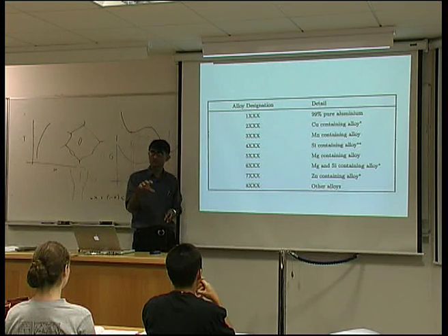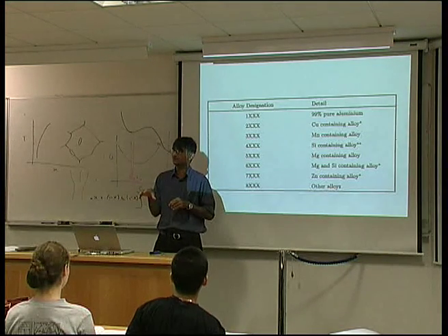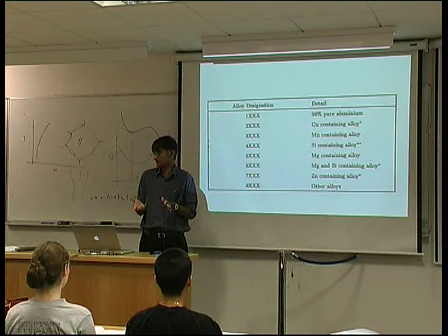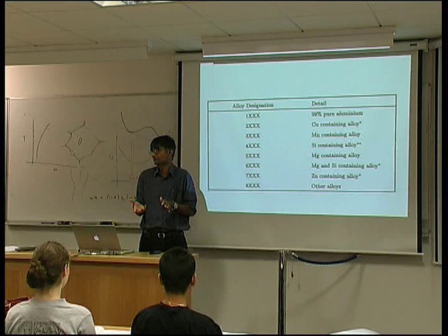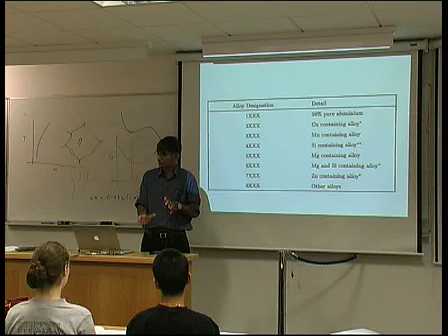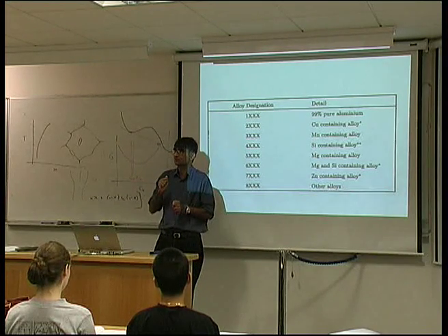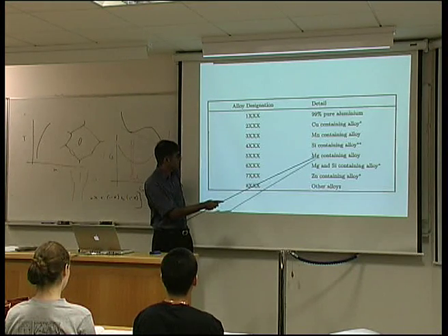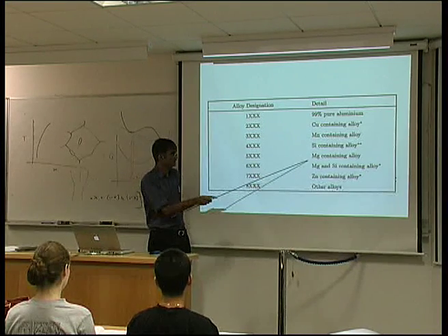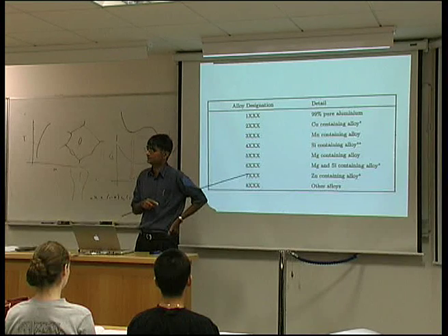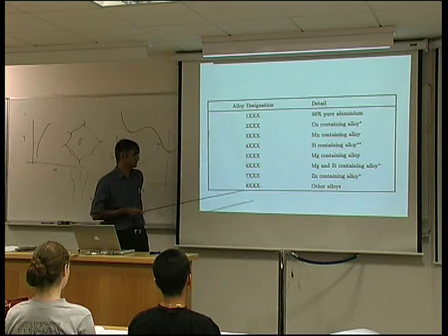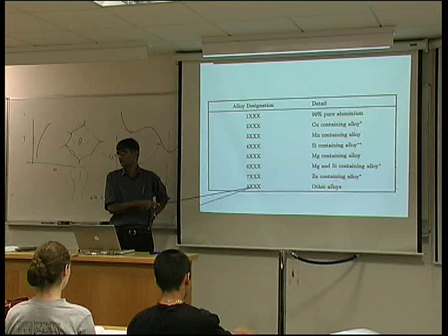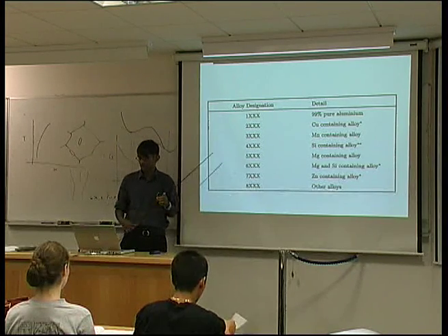So it makes for a very good casting alloy. If you look at the engine blocks in modern cars, they used to be made out of cast iron, but almost all of them are now made out of aluminium silicon alloys because it's got a lower density than cast iron. You might have a lining of steel or cast iron where the pistons are, but essentially it's aluminium silicon alloys. These alloys are used in marine applications. They contain large concentrations of magnesium, of the order of 3 to 4%, to help give corrosion resistance. And then we get to specialized alloys here. For example, here we might have oxide dispersion strengthened aluminium, where we deliberately introduce alumina into the material.